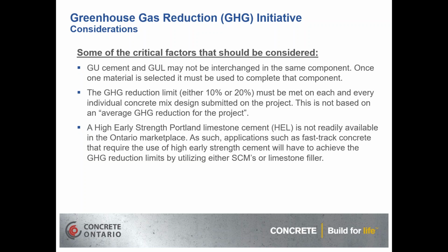And another consideration is that a high-early strength Portland limestone cement is not readily available in the Ontario marketplace at this time. So as such, some applications, particularly fast-track concrete, that requires the use of high-early strength cements, will have to achieve the greenhouse gas reductions by utilizing the SCMs or the limestone fillers, which can be challenging with higher SCM replacement levels to try to get those high-early strengths. So this is something where you might consider talking with the CA to see if you can maybe get an exemption for that particular mix, if they will allow that.